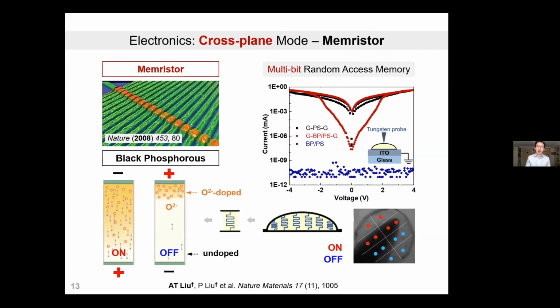So to answer the second question, the memory resistance is actually quite stable. So it's non-volatile. I have obviously not tracked the memory resistance to its failure, but it can stay there for days on end without really a decrease. One of the reasons is that we have to bear in mind that our memory resistance pathway across the particle is at least 1 micron in length. So this is quite a long pathway, meaning that you actually have to spend more energy than these nanoscale, for example TiO2, or these very small nanoscopic memory resistor devices that people use for neuromorphic computing. So the switching time is obviously not comparable. But the advantage is that it's quite stable, right? Once it's turned over, it takes a lot of effort to then drive back the oxygen defects in the reverse direction. And so it's quite stable in our testing.